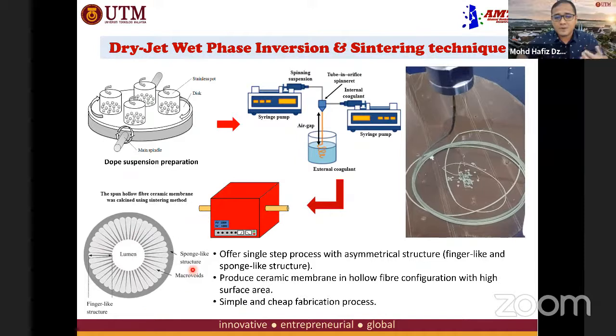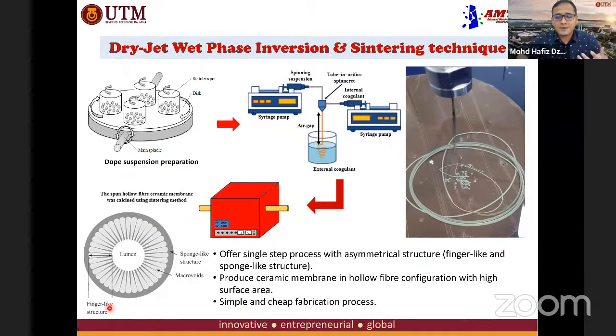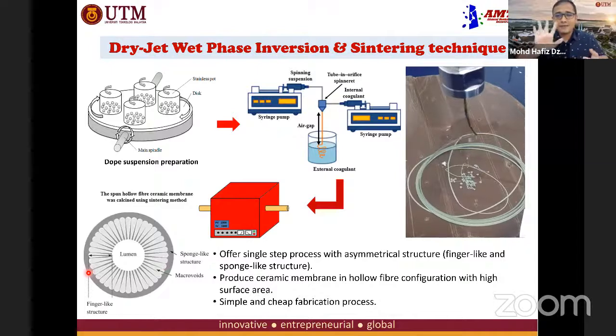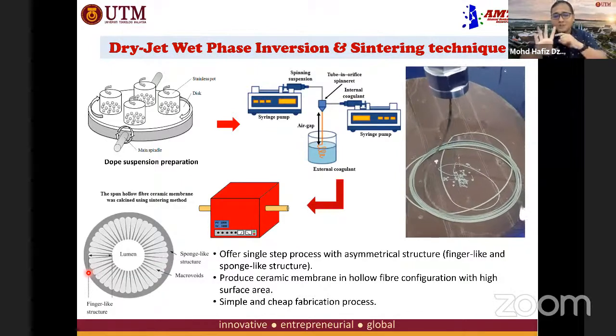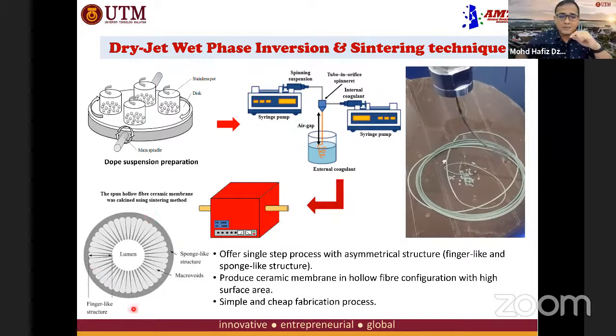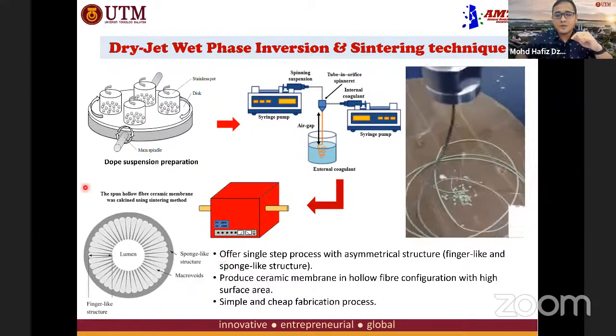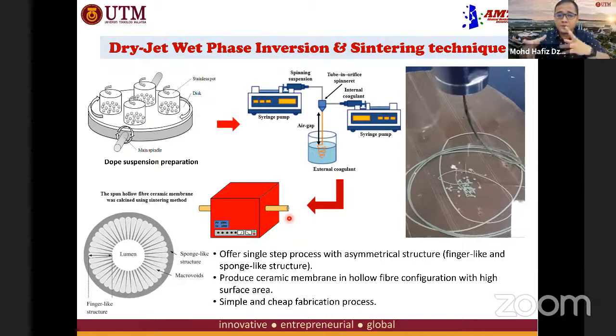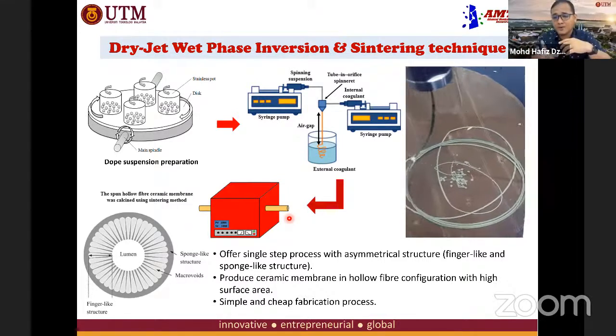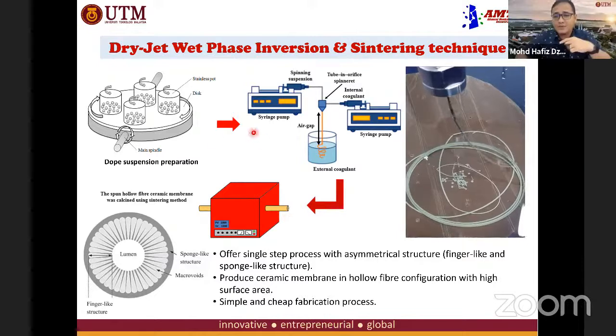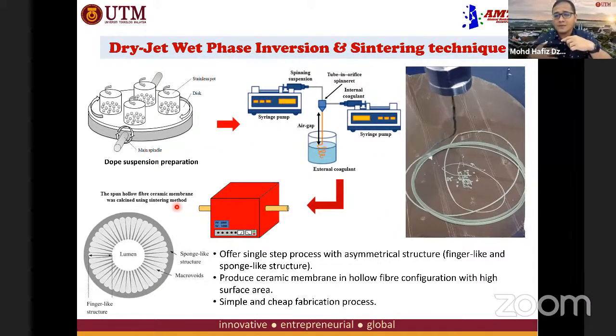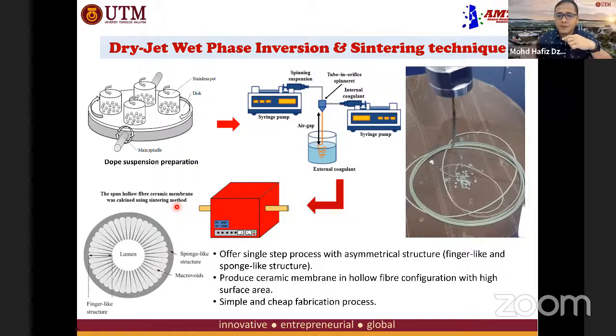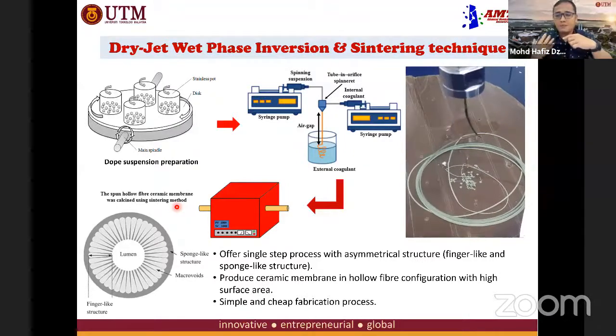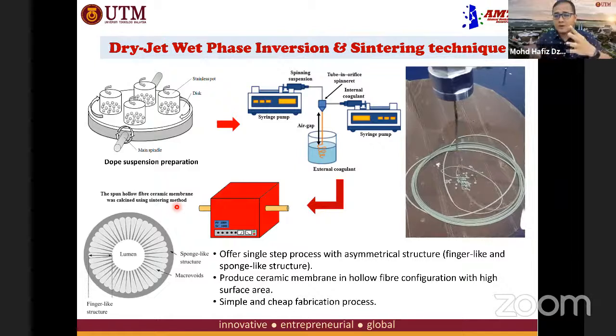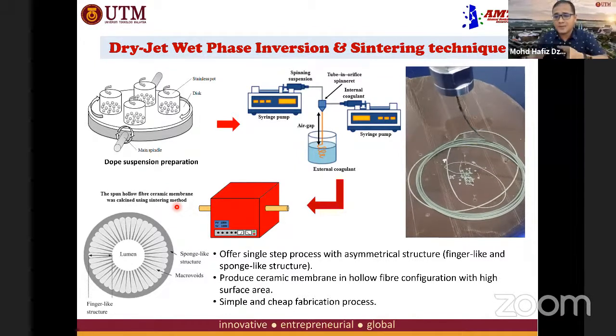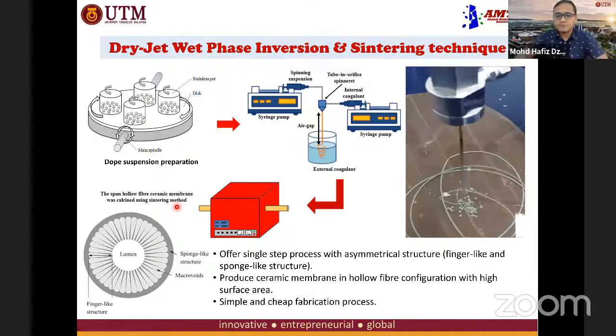So the asymmetric structure is composed of macrovoids. Normally the structure is like a finger, that's what we call a finger-like structure. And on the outer, there is a sponge-like structure. Okay, so this precursor also contains some binder, normally we use polymer as a binder, so we have to sinter it. During the sintering process, most of the moisture, the retained water, polymer, and other impurities will burn off, and what is left is pure ceramic after the sintering process.